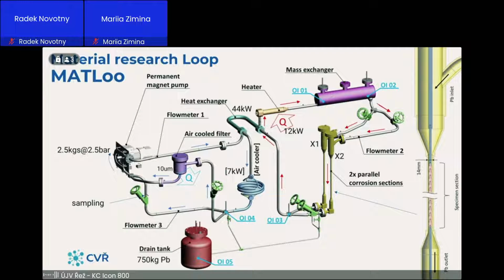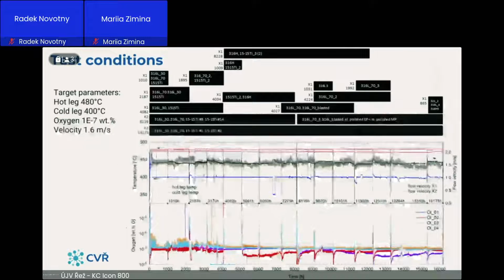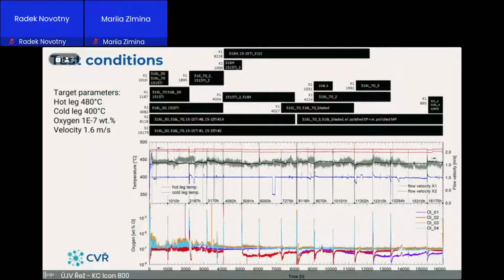We place them into a corrosion loop that is non-isothermal. It has a hot leg and a cold leg with a cooled filter. In the hot leg, there is a mass exchanger to allow us to control oxygen content. There are 2 parallel corrosion sections where specimens were placed in the manner shown in this picture. And there are 4 oxygen sensors: one at the inlet and outlet of the mass exchanger, one in the hot leg tube, and one in the cold leg tube. So there is a record of this 20,000 hour-long experiment.